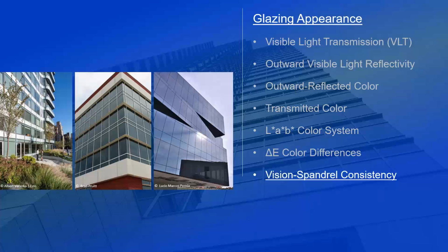The middle example is with tinted glass, where the same tinted low E glass, with low reflectivity because the glass is tinted, is absorbing more solar energy. Tinted glass with a low E coating used for both the vision and the spandrel can provide good harmonization. And then reflective glass, which is what you see on the right, is a reflective low E coating on a clear glass substrate used for both the spandrel as well as the vision glass, with a nice opacifier on the number 4 surface. That's also a good option, although both the option in the middle and the right are going to cost the project more at construction compared to the monolithic spandrel glazing on the left.